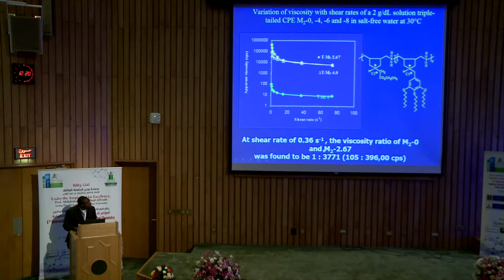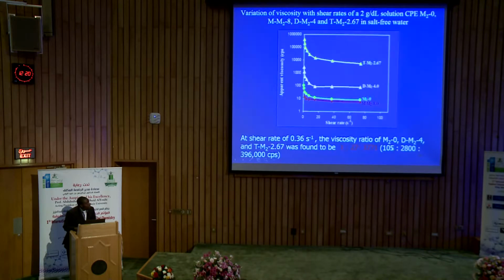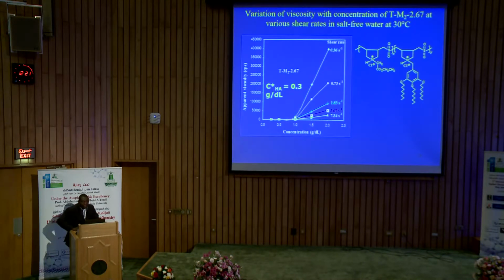Then we try the triple tail. The viscosity is also tremendously increased, 105 centipoise, and the triple tail gave us almost 396,000. Which shows that it is nothing but intermolecular association, which leads to a dramatic increase in viscosity. We also try viscosity at different shear rates, because the shear rate also affects viscosity. This is without hydrophobe, this is with the mono, this is di, and this is tri. And then we measure the intrinsic viscosity against concentration to determine the critical hydrophobic association concentration. What is reported in the literature so far is around 1%, but for triple tail, we achieve a critical hydrophobic association of 0.3%, which is a big achievement.